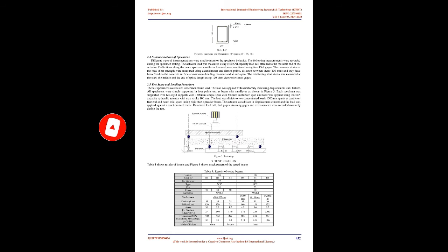The behavior of the beams was similar in the 3 series of tests, even considering the low ductility of one of the 3 mixes. 12 beam specimens, 2000*300*200 mm, were tested under positive bending. A loading system was used to determine the effect of SCC and reinforcement diameter on bond slip characteristics of tension lap splices. The beams of the lap splice group were tested with lap spliced bars in the midspan, in a region of constant positive bending. The results showed that load transfer within the tension lap spliced bars in SCC in an RC beam was better than that of the tension lap spliced bars in NVC.